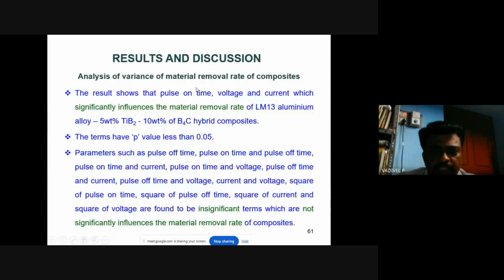Here is the ANOVA table for the metal removal rate, MRR, of the composite, with pulse on time, voltage and current as parameters. With these parameters, the influence on the MRR of the aluminum composite is significant, with a maximum at level 5. The terms have p values less than 0.05.